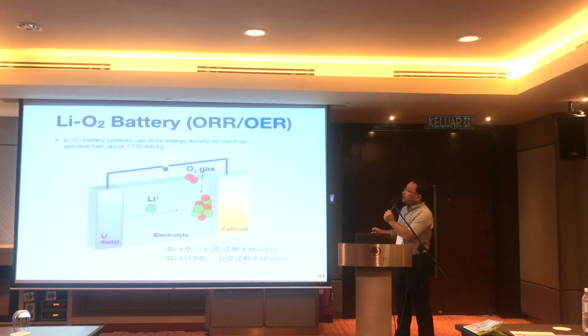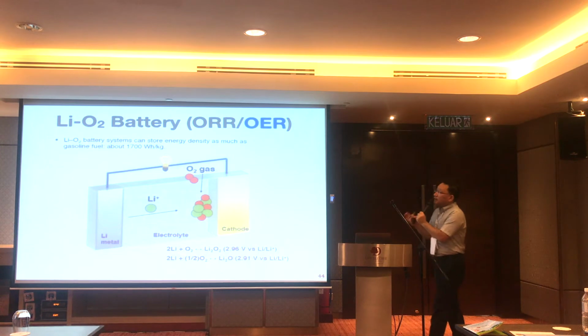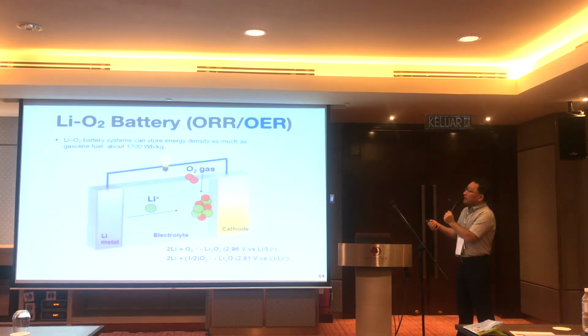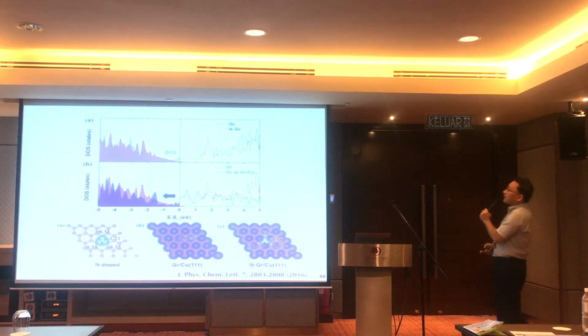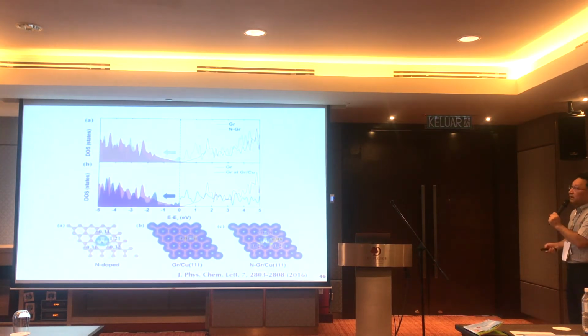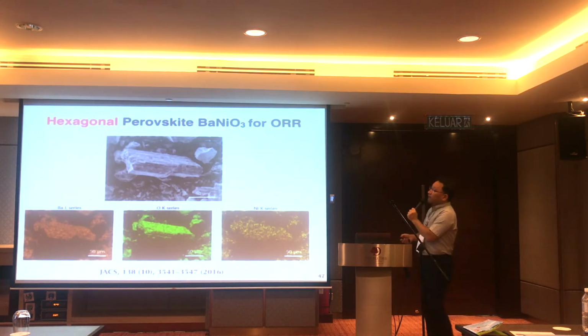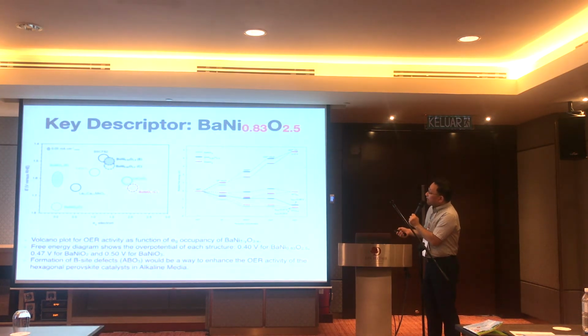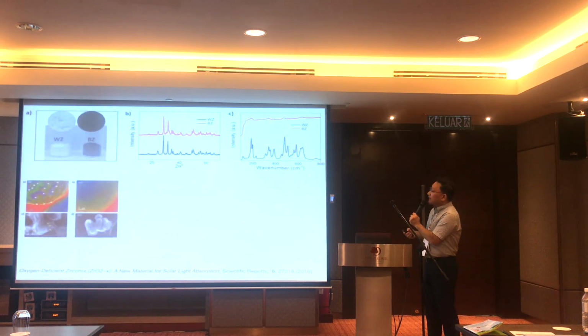We also worked on lithium oxygen batteries, lithium air batteries. Here the key issue is the oxygen evolution reaction. Oxygen evolution reaction is the key reaction in the lithium air battery or photocatalyst by water splitting. So we figured out that here nitrogen doped graphene is quite good, or nitrogen doped graphene overlaid with copper is quite a good catalyst material. Or hexagonal perovskite with a certain amount of defect is going to be the best. We published in a JACS paper two years ago. We figured out that if you have a certain amount of oxygen defect, then you're going to reach the best performance.